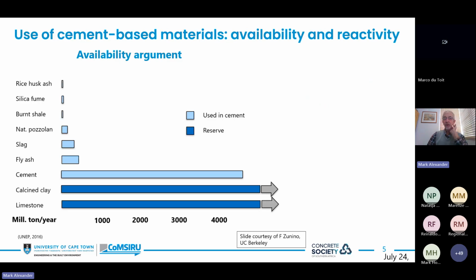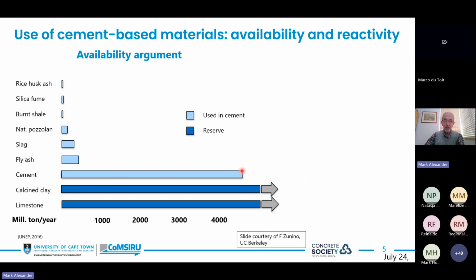Here's another one, the question of the use of cement-based materials on the basis of availability and reactivity. If we look at the availability of cement-based materials, now we're switching over to these materials, you can see that if we go further down here to the cement, let me just find a pointer here. There we go. If we look at cement, of course, we're making a lot of it, over 4 billion tons, although that's starting to come down, with China now cutting back significantly. With the other materials here, rice husk ash, silica fume, burnt shale, natural pozzolan, slag, fly ash, and so on, relatively small quantities. I think with the fly ash, we've got quite a lot in South Africa, so this graph doesn't reflect that, a reserve.